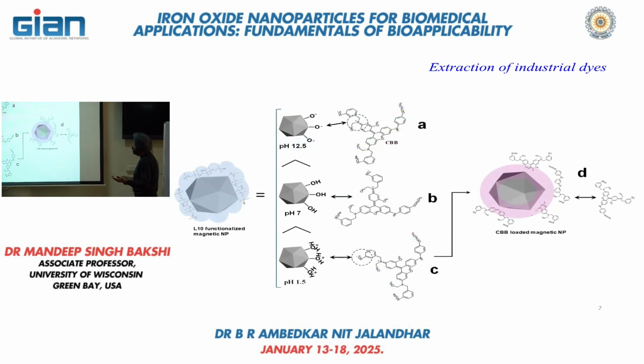So how is the extraction happening? The brilliant blue is showing the maximum extraction in the acidic medium rather than the basic medium. Here is the story. In the basic medium, the hydroxyl groups are deprotonated, right? They are negatively charged. The negatively charged groups are not going to interact with the sulfonate group. So this is the sulfonate group of the brilliant blue.